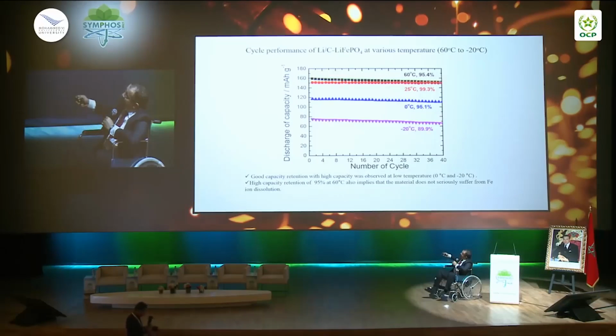And these are some of the cycling performance. As you can see, at different temperature, it is very stable. It's very stable because of the nature of the material. Iron phosphate, as I mentioned, you oxidize iron to 3+, and 3+ is very benign to reactivity with the electrolytes. You don't see any surface reactivity that leads to impedance rise and degradation of performance.